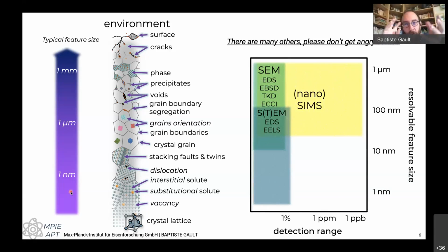And when we start thinking a little bit about materials characterization, there's a number of techniques that spring to mind beyond optical microscopy. There's all of the scanning electron microscopes and transmission electron microscopes, sometimes also operating in scanning mode. And then what we often want to do is look at the microstructure, the structure of the atoms, but also what is the local composition? What is the local mixture of different atoms from different elements? And for this, we can use, for example, EDS, or X-ray energy dispersive spectroscopy, or EELS, so when we look at how the electrons lose energy as they travel through the sample, and then we can get from this a number of pieces of information on the local composition.